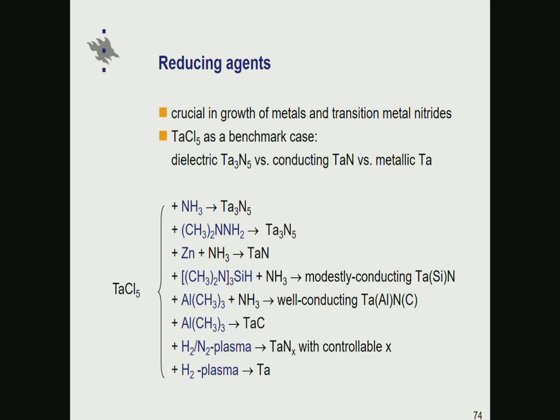So basically by comparing different reducing agents, one can rank them, so what is the reductive power in ALD conditions. For example, with ammonia or dimethylhydrazine, there is no reduction taking place. If one adds elemental zinc, one gets metallic tantalum nitride, but nobody wants to have zinc in a semiconductor environment at least. Then there are alternative reducing agents like trimethyl aluminum. So trimethyl aluminum is producing well-conductive tantalum aluminum nitrocarbide. If you think about this phase and the aluminum carbide phase alone, they are both insulating. So that shows that in this case, TMA is reducing tantalum. And eventually when going to plasma conditions, one can produce tantalum nitrides with controllable x, and with hydrogen plasma also elemental tantalum, at least with some level of success.